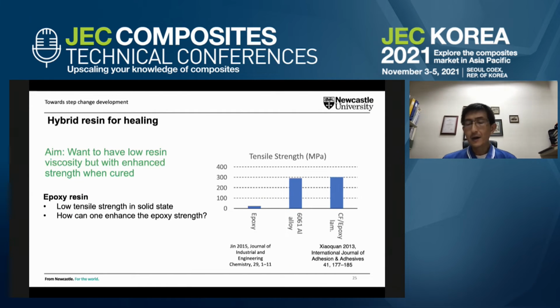We also looked at developing resin for the healing process. So our goal is to have low resin viscosity, obviously, so it can flow much better through the cracks, but also it contributes to shorter repair time as well. But we also want to see, clearly, if epoxy is used in the repair, most times, for instance if the matrix is made from epoxy, then you use epoxy resin. But we also want to know if we can enhance the typical resin like epoxy, for instance, by enhancing its strength when it's cured.